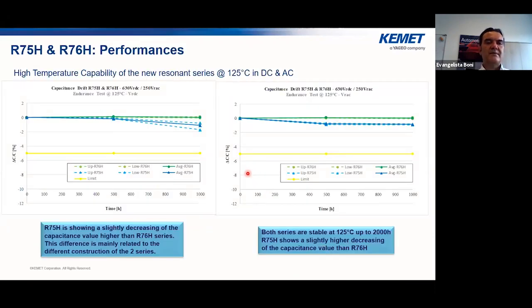Here we can underline some performances of R75H and R76H. On the left, we can see the capacitance deviation up to 1,000 hours at 125 degrees, performed at rated voltage. We can see that both series are quite stable. R76H is a little bit more stable due to the double metallization construction, but R75H is also quite stable. It's also seen, not shown here, that at 105 degrees both series are stable for more than 3,000 hours. So that's a great achievement.